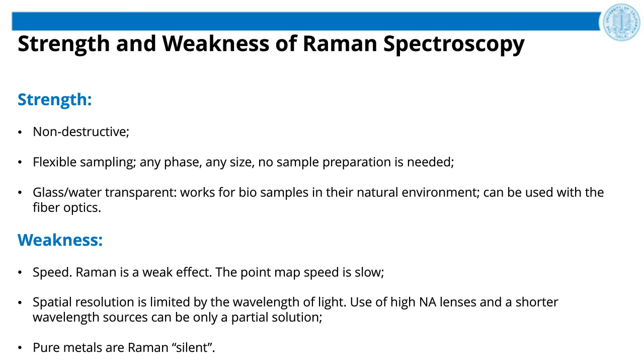Well, another problem is spatial resolution. Because it's a light-based technique, it's limited by the wavelength of the light, according to the Rayleigh criterion. A partial solution can also be found by using high numerical aperture lenses or shorter wavelength sources. However, it's still not completely satisfying. This problem can also be solved by coupling Raman with SEM. We know that scanning electron microscopy can provide nanometer resolution.